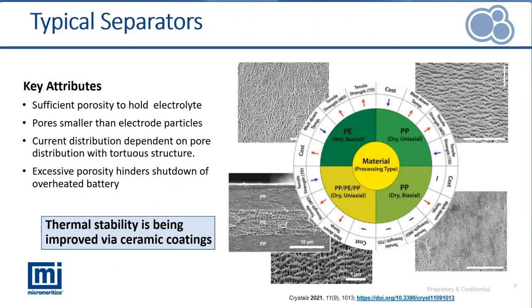There are several different types of separators used, in the different types of technology. You can either have polyethylene or polypropylene. You have different types of processes, wet and dry process, and then you can either biaxially or uniaxially stretch these. Depending on what combination of these you choose, you have differences in cost, the mechanical performance both in the transverse and machine direction, as well as what temperature the separator will shut down the battery at. At the top, you see both the polyethylene wet biaxially stretched and the polypropylene dry uniaxially stretched.